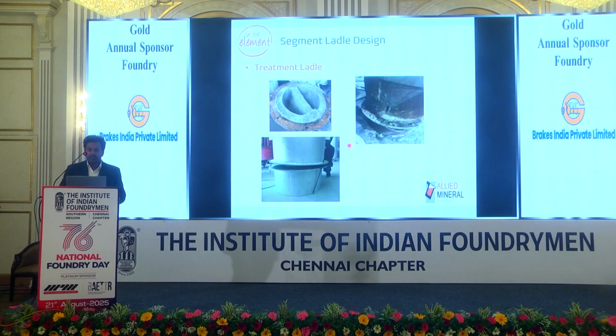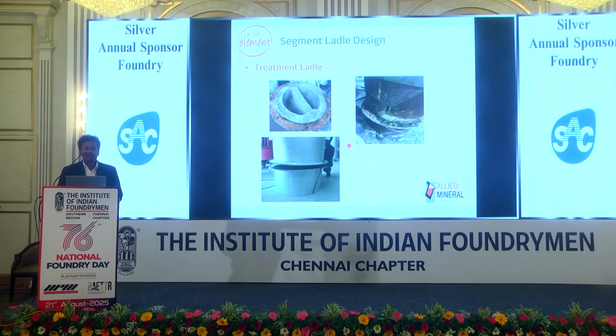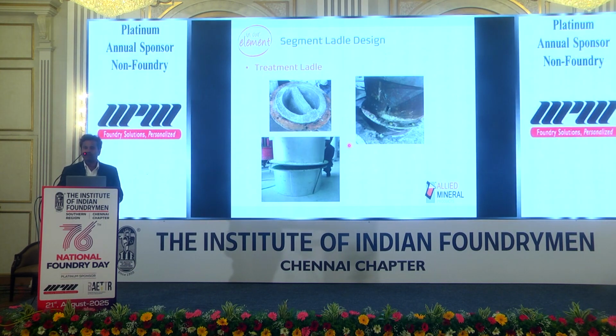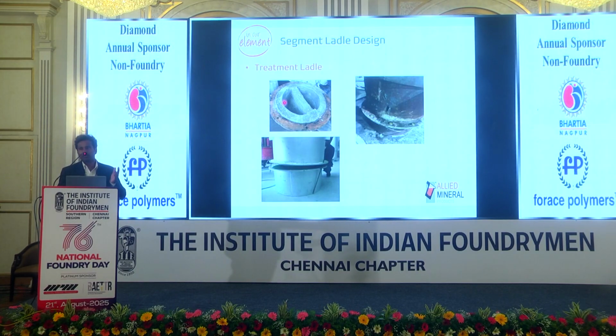Now we'll see some design parameters and how we can improve productivity. A treatment ladle is generally designed such that the diameter is 1:2 of the height. So if it is 500 millimeter diameter, the ladle will be 1 meter in height. It will always be difficult to maintain this pocket or treatment area. Because the height is more, a person cannot go inside and do the refractory repair work. Moreover, the exothermic reaction happens in this treatment segment.